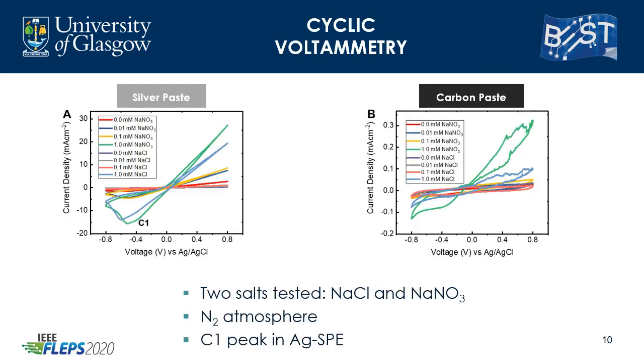So let's analyze the voltammetry experiments for the silver and carbon electrodes. We chose two common salts for our experiments, sodium chloride and sodium nitrate. All studies were performed under nitrogen atmosphere. The observed current density level for the silver electrodes was almost 100 times higher as compared to the carbon ones. This could be due to the high conductivity of the silver electrode and the faradaic reaction of the electrode